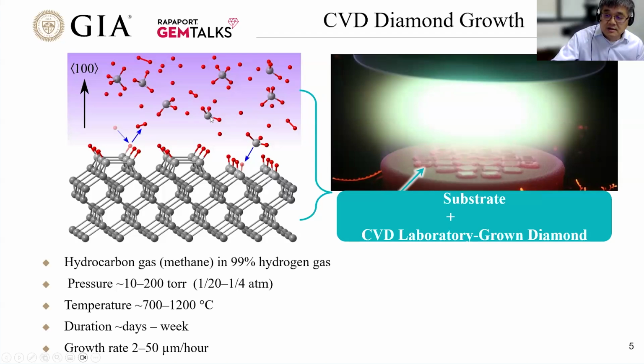So some ionized carbon could deposit over the diamond seed here. We show the lattice here, growing layer by layer as a diamond. Even at such a low pressure, it is still deposited over the lattice as a diamond. It is an amazing technology. We can grow diamond in the graphite stable area. Similar to the HPHT method, multiple crystals could be produced simultaneously with CVD technology, with a speed of about 2 to 50 microns per hour. So we can easily calculate that it takes a couple of weeks to grow a decent size gem diamond. Again, instead of one crystal, they can grow up to a few dozen crystals simultaneously.